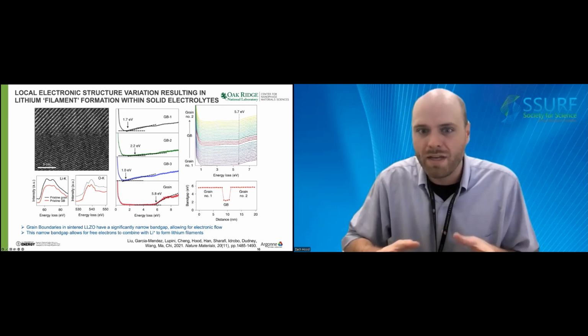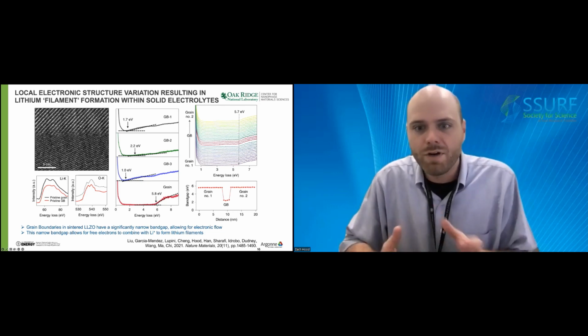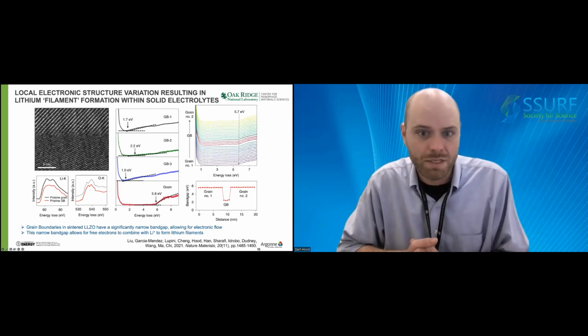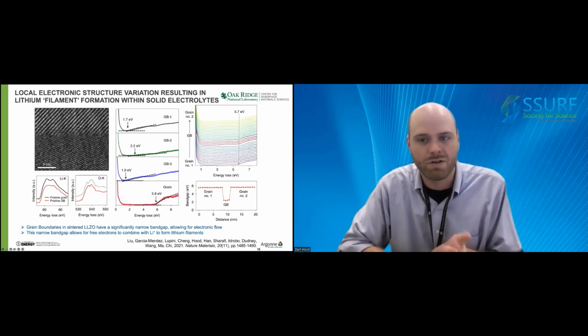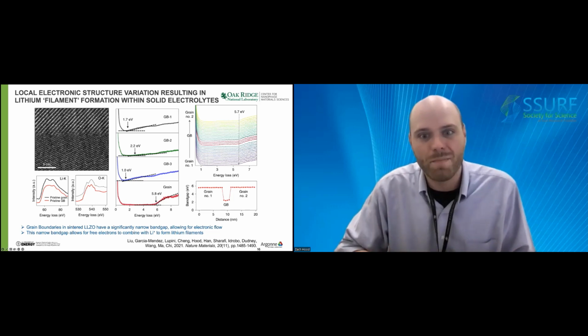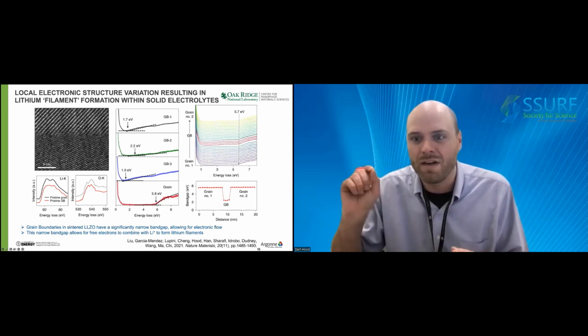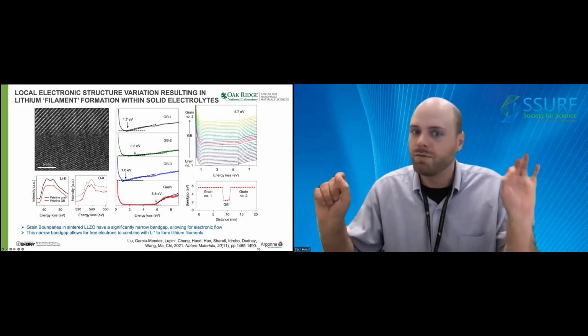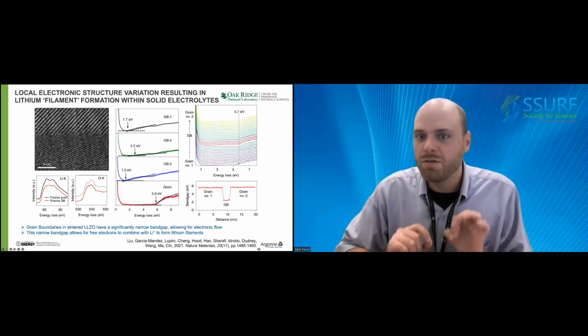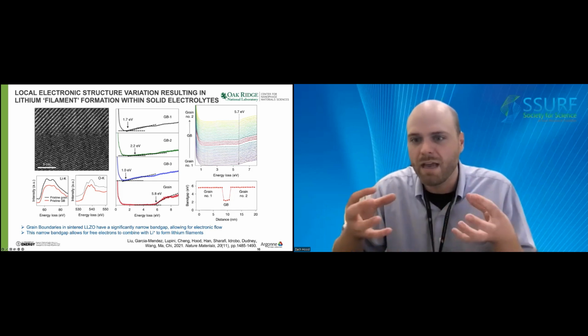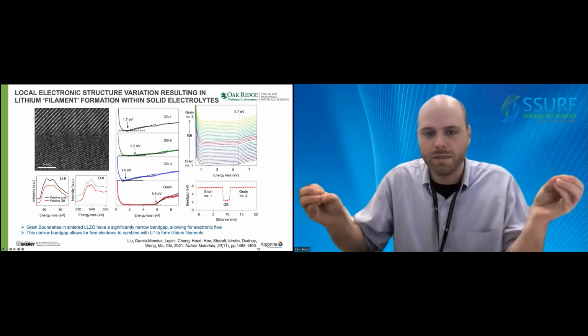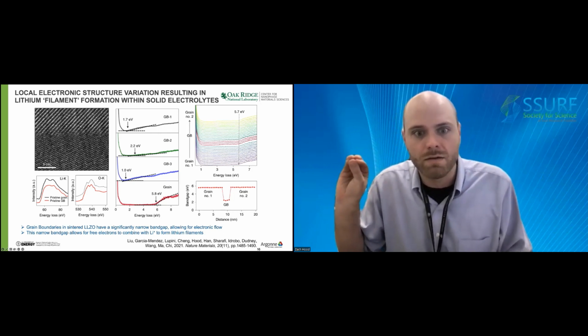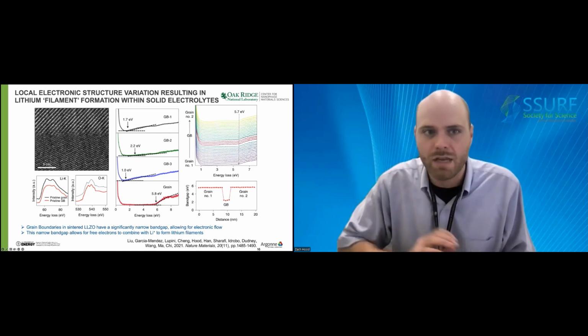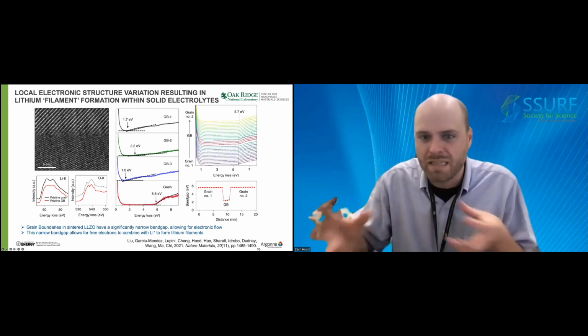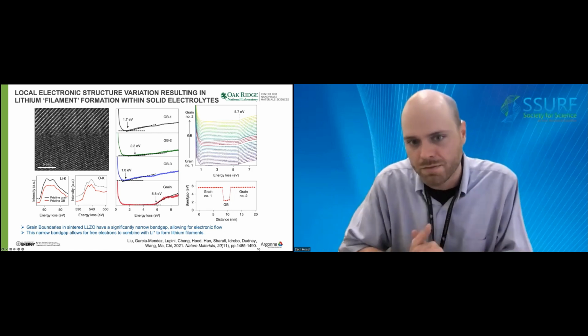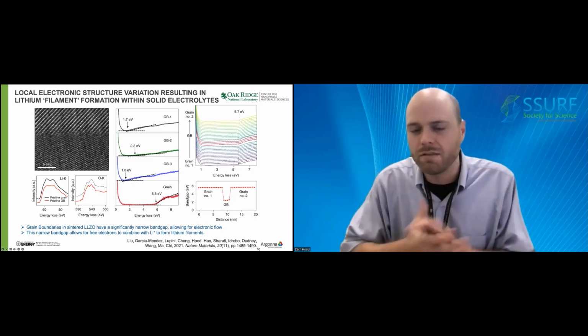So to interrogate this point of the influence of the grain boundary chemistry, we leveraged advanced scanning transmission electron microscopy and valence band electron energy loss spectroscopy in order to reveal the local atomic and electronic structure difference at the grain bulk and at the grain boundary of lithium garnets. Specifically, we use this unique capability to show the band gap of the grain bulk and how it compares to that of the grain boundary. At the grain bulk, we measured the band gap in the material to be around 5.7 to 5.9 eV, so it's mostly insulating and compares well with what's theoretically predicted for this material.